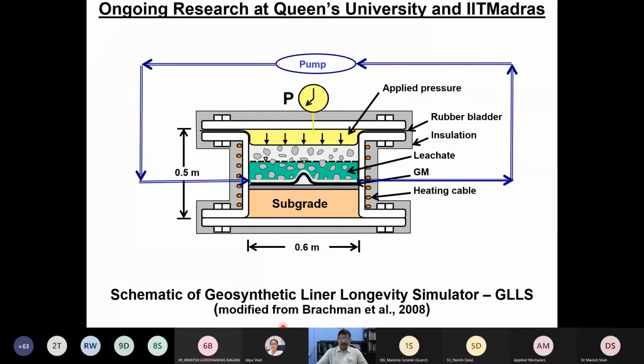But the beauty of this particular cell is that you can simulate various proportions or configurations of your liner system. I can simulate a wrinkle. I can place the leachate collection system, maintain the leachate head, and recirculate the leachate the way it happens in a landfill. We can maintain the temperature of the geomembrane and the entire components using a heating cable, then put a nice insulation jacket, and apply physical loading up to around 1.2 megapascal.